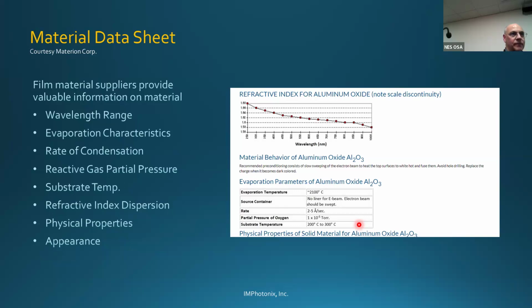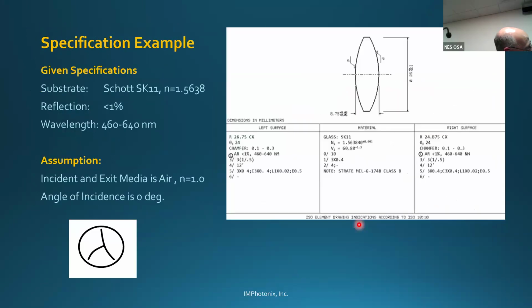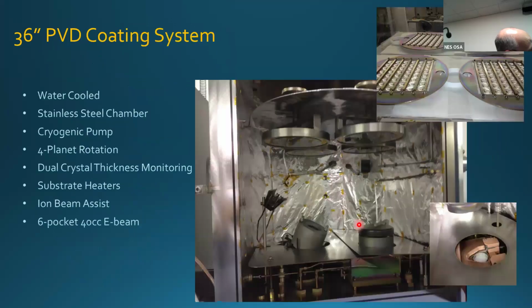Do you load the machine with more than one coating material and somehow rotate it in? Yes, good question. The E-beam gun here, in the lower right corner, is a 6-pocket E-beam gun. Each material is in a 40 cc crucible, and so we can put in up to 6 crucibles of the same material, 3 of tantalum pentoxide and 3 of SiO2 if it's alternating materials. If it's a 3-layer coating, we'll put in 1 crucible of aluminum oxide, 1 crucible of tantalum pentoxide, and 1 crucible of barium fluoride. And so we can alternate between those materials.